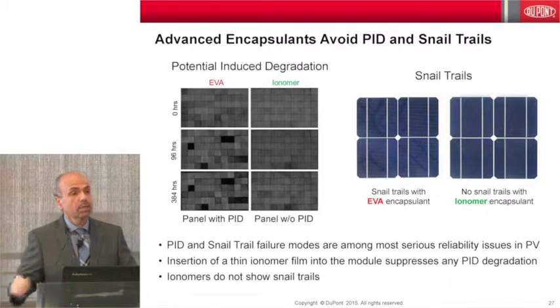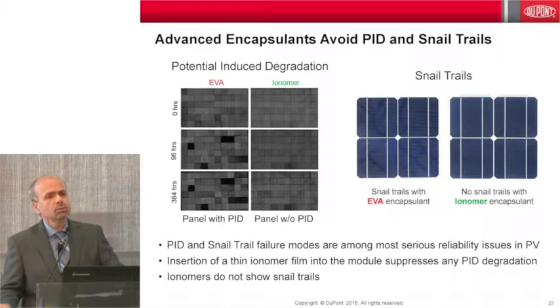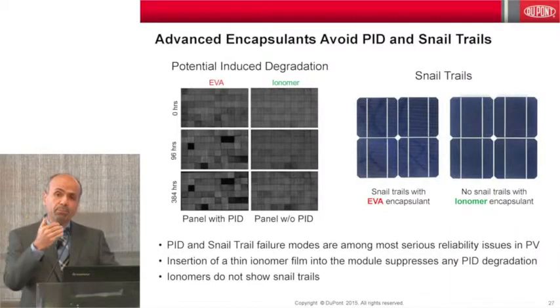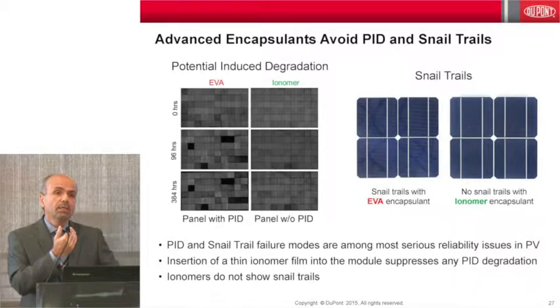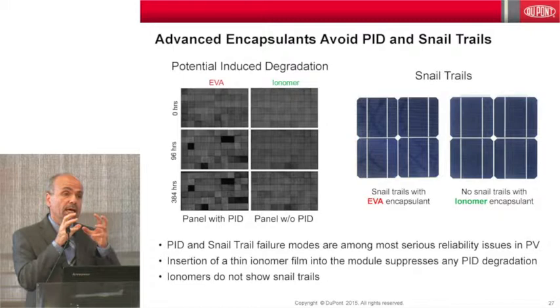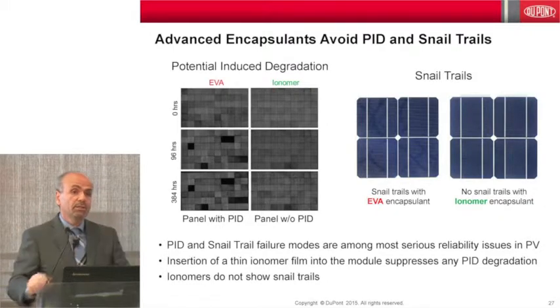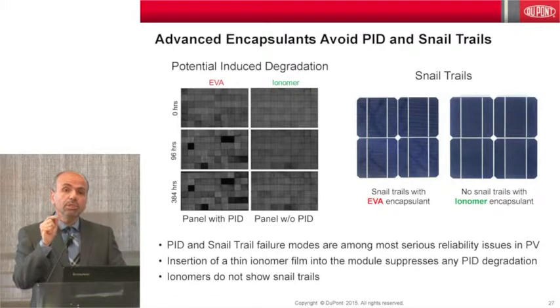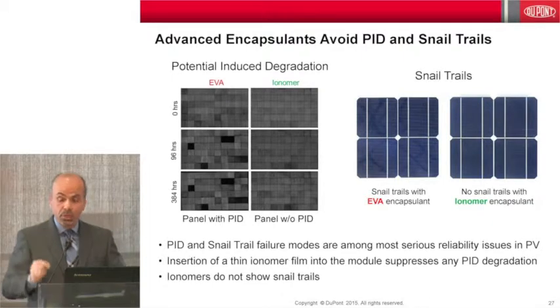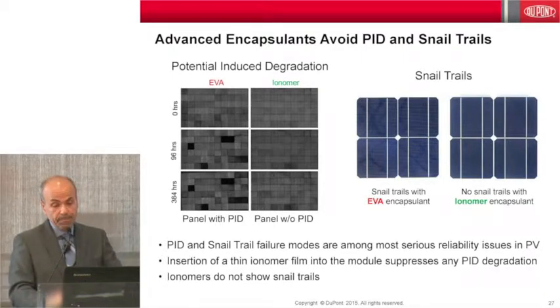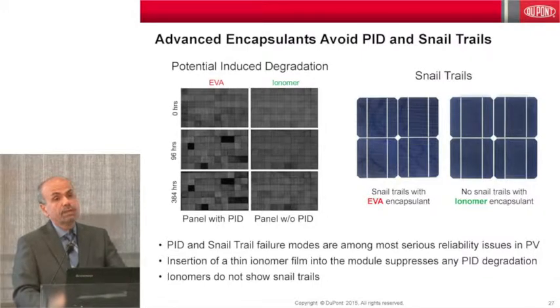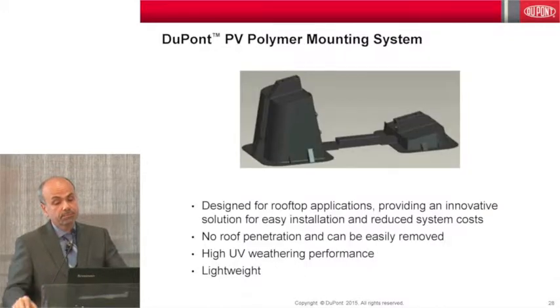Today's modules employ cells that are close to 200 microns or 180 microns, and you can crack them very easily. So water that permeates through these cracks interacts with the encapsulant, creates acids, and those acids attack the silver. So you want to use encapsulants that don't have byproducts of that sort. And the ionomers actually have proven to provide this great protection.